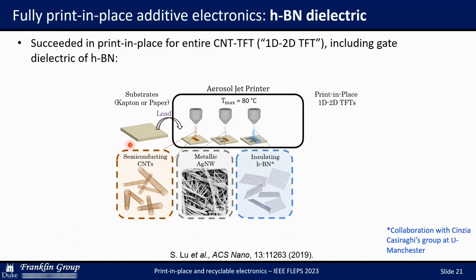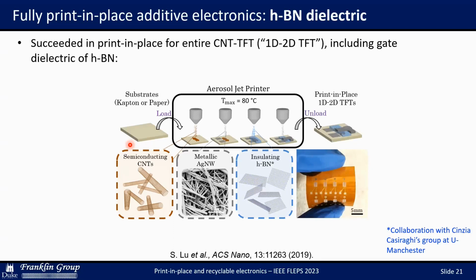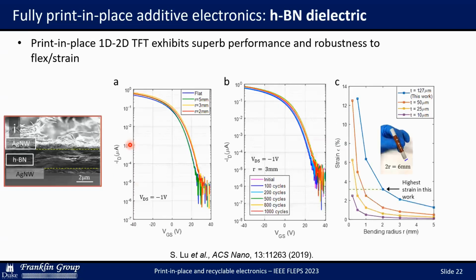This ink was developed in collaboration with Cinzia Casiraghi at Manchester. And then finally, we printed a conductive gate electrode. And as the cartoon had shown, immediately removing this, it did not go to the oven or the hot plate. It just went to the probe station, and the transistors were fully functional. In fact, the performance we tested, including their flexibility or operation under strain, which those that were printed on Kapton